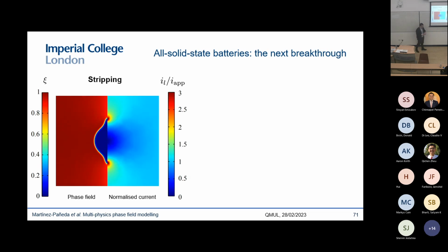And just to show you some representative results, this is stripping of a single void. And you can see that we see what we expect from the experiment. Here you're seeing the phase field, so you're seeing the void growing, enlarging in the vertical direction, which is exactly what we saw in those experiments of Peter. And naturally the model is able to capture those current hotspots in the electrolyte. You can see these regions where the current is localized in the void.